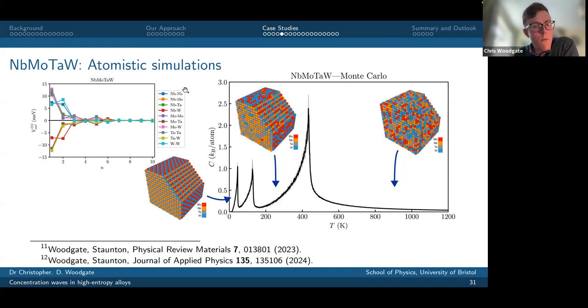So what I wanted to highlight just here is in the top left panel, I'm plotting the effective pair interactions as a function of coordination shell number, so nearest neighbor distance, and you can see that these effective pair interactions are dominated by the first 2, 3, but by the time you've got out to 6 coordination shells, you've got all the information you're going to get out of there. So there is definitely a finite range to these interactions in most of the systems we've looked at. It's not always true, but in these high entropy alloys, we've generally found that things are pretty short ranged.